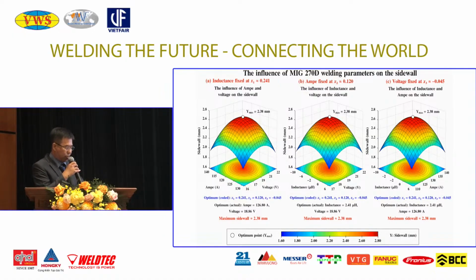The interaction between weld current, voltage, and sidewall is evaluated by fixing one parameter at its optimized value. Based on the result of 6061-T6 aluminum weld using MIG 270D, the variation of the other two parameters is analyzed in relation to sidewall penetration.